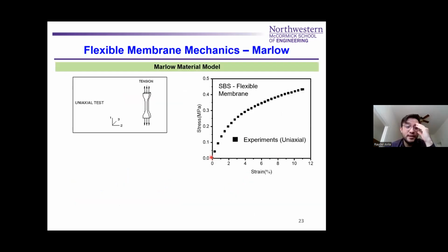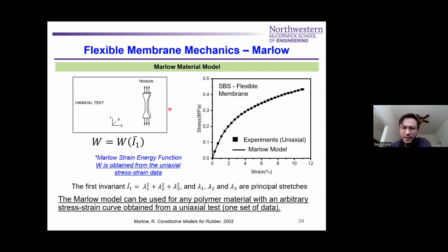But more interestingly, let's say that you have some material and you have some data for stress and strain. So you have some experiments, and your material is going to be SBS, a block copolymer material. You test it and find what its stress-strain curve is going to be. Then you can use the Marlowe model. This is a hyperelastic strain energy model where the strain energy function is built directly from the first invariant, given by the stretches written right here.